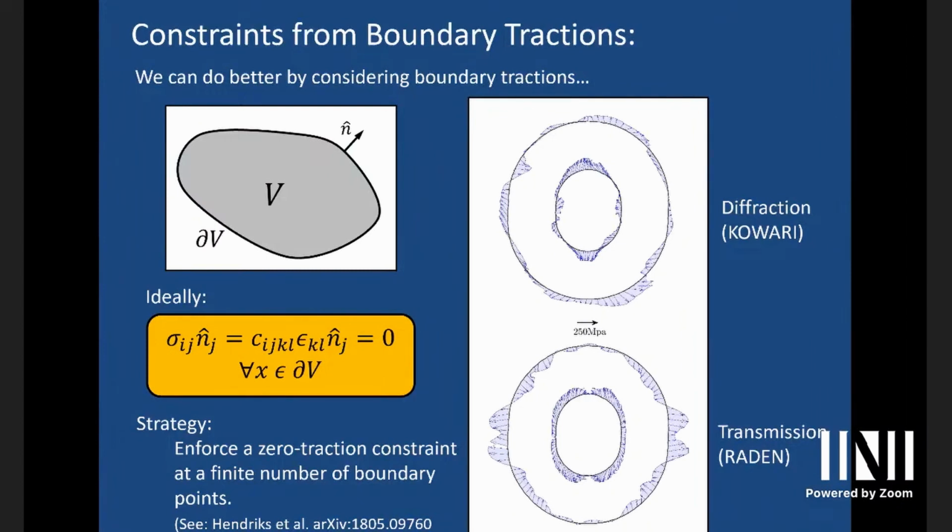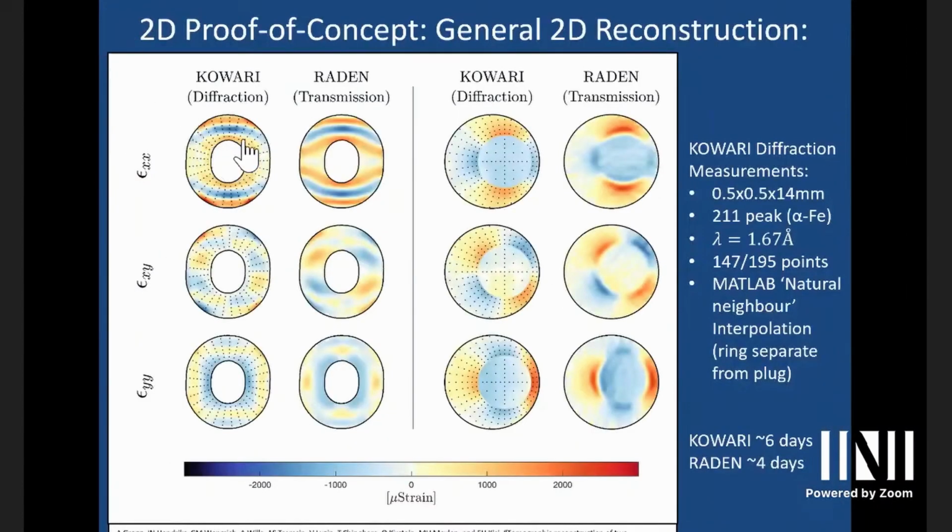And I'm not saying that the measurements are wrong. I'm just saying that the first thing that happens when somebody measures a bunch of points like this is they interpolate the field out to the boundary, and you can't measure at the boundary. It's not possible to measure at the boundary. You get systematic errors if you do that. Certainly the extrapolation to the boundary is just being done by whatever algorithm you've chosen, so it doesn't have to satisfy equilibrium, and it doesn't, right?